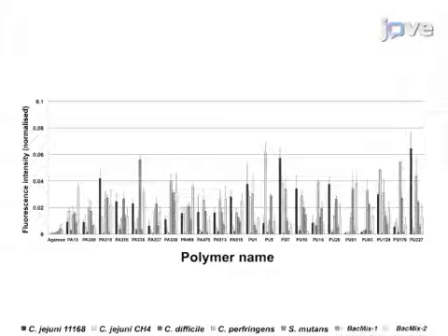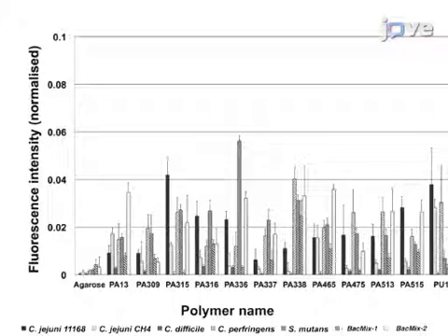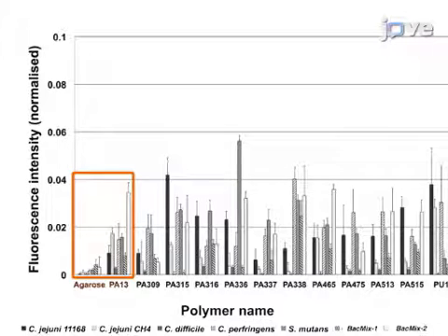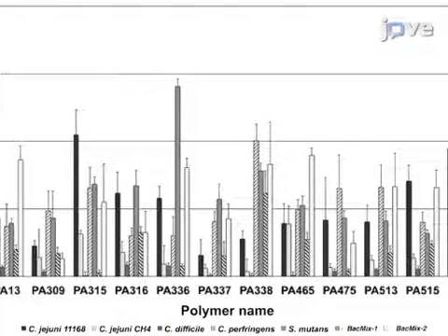This figure shows bacterial attachment to a number of polymers as determined by microarray analysis. Spots printed without polymer act as the negative control, as agarose strongly resists bacterial binding and thus fluorescence is very low. The polymers displayed are all low binding, although in most cases the repellent properties of a polymer vary significantly between bacterial species tested. This reflects the wide differences between attachment mechanisms across different species.